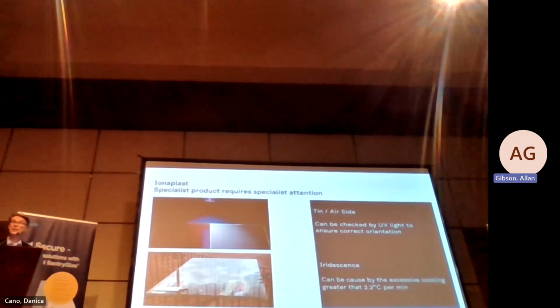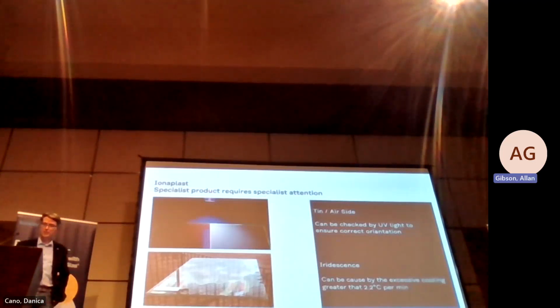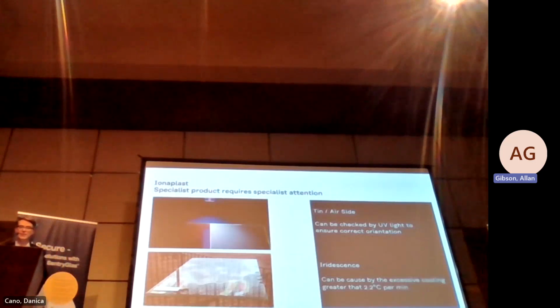Now, the autoclave, or the pressure cooker that the laminated glass is put into to disperse the air during the processing, needs to be rapidly cooled, a bit differently to a PVB. Cooling SentryGlass at a rate of 2.2 degrees Celsius per minute will help to reduce that risk of haze, which can often be associated with SentryGlass also. However, if you cool it down too fast, then you have a risk of producing iridescence. So it's almost like black magic.